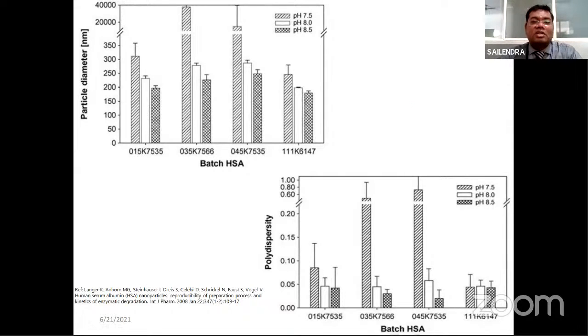Second most important part, composition of the protein. Now the composition of the protein is going to decide the isoelectric point of the protein. Always remember, I'll come to that point also. Your window from the isoelectric point should be so huge that you can tweak in that window. Suppose the isoelectric point of the protein is 5.3 and we are working at a pH of 8.5. Then you have better chances of getting consistent nanoparticles at pH 8.5 compared to 7.5, because pH 7.5 is close to the isoelectric pH of the protein, that is 5.3.